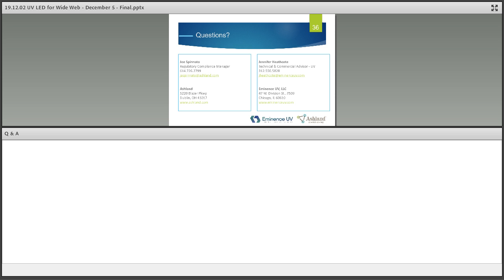So here was one question that popped up. Can you cure through opaque? So one of the huge advantages that LED technology offers is because the wavelengths are longer, they're in that UVA region that's closer to the visible. Those longer wavelengths from the earlier slides in the presentation, they actually penetrate all the way through. So what that means is when you have opaque formulations, whether it's an ink, a coating, or adhesive, if there's some sort of an additive in there, typically what those additives do is they either block, reflect, or scatter the light. Well, many of the longer wavelengths don't get absorbed by those additives.